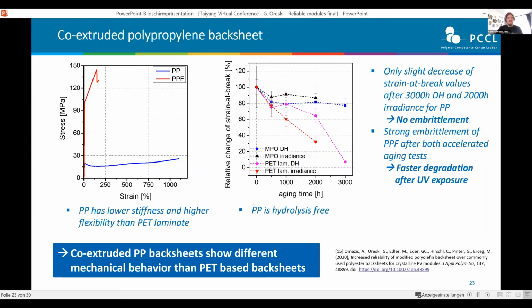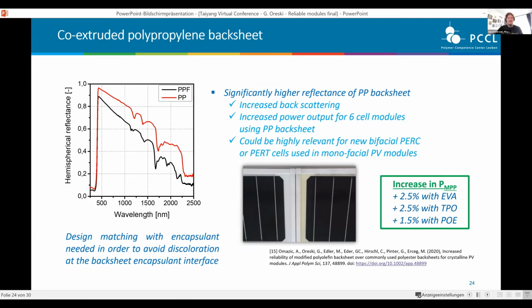What are other properties? They are quite white, at least this material we had, so it had a much higher reflectance. And actually that led to an increase in power of, let's say, 6 cell modules from 1.5 to 2.5%. So it's quite a nice thing. Instead of the grid we heard before, also use a very white backsheet and you will get some power gain. But in any case, we observed yellowing at the backsheet encapsulant interface. And that's what I said. Some additives are migrating in there, reacting and causing this bad color. So you should really do your design matching in order to make it work.